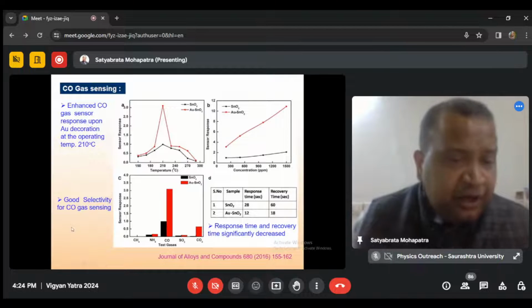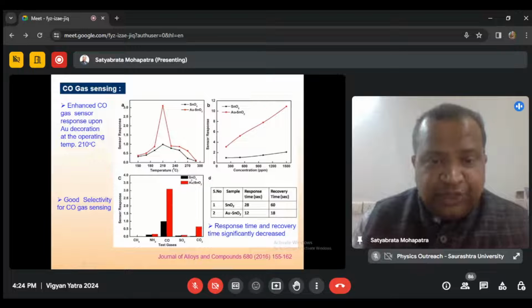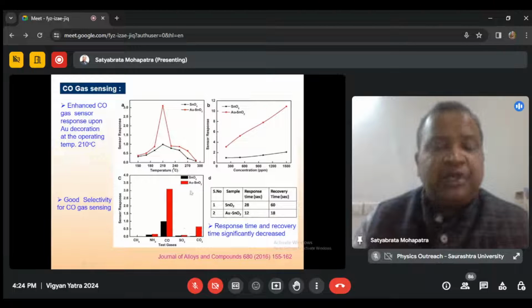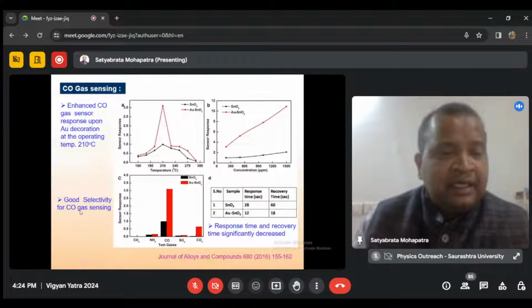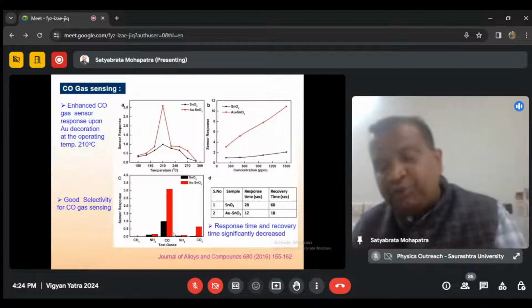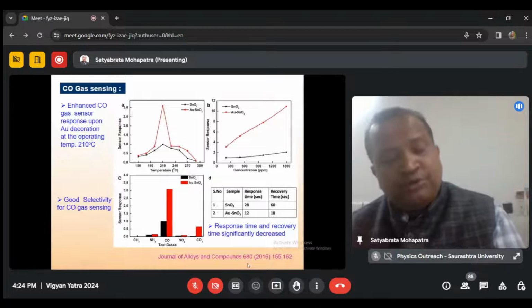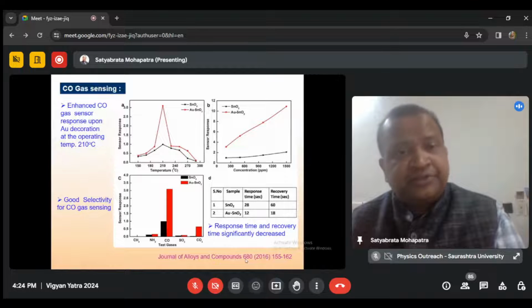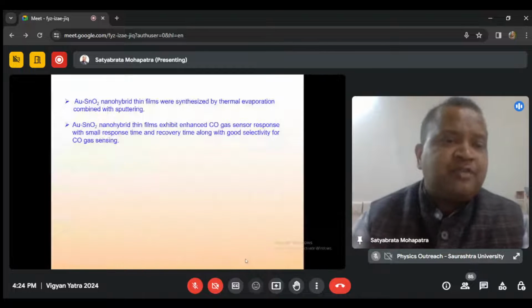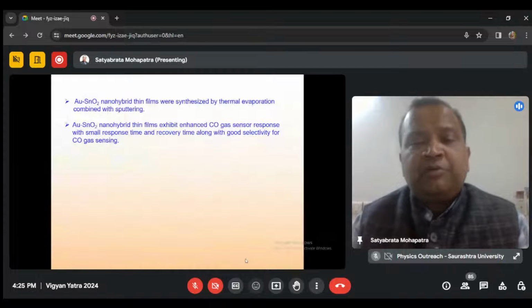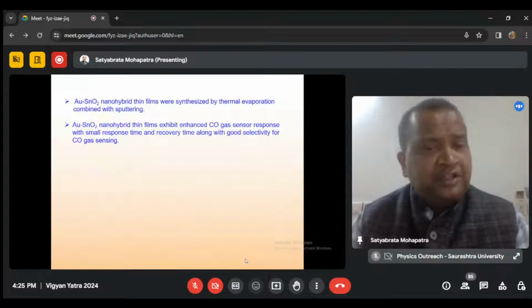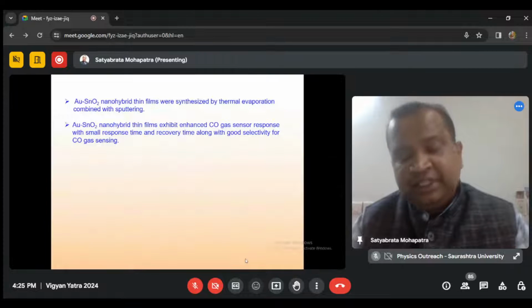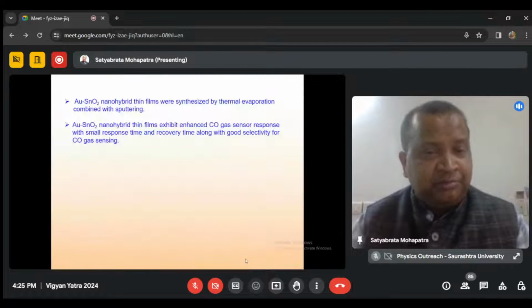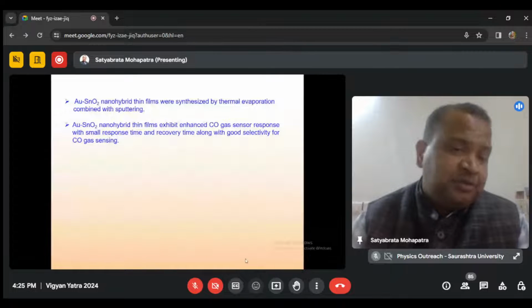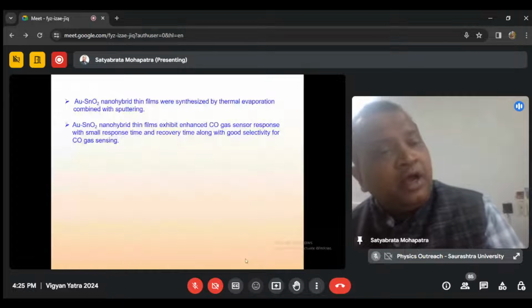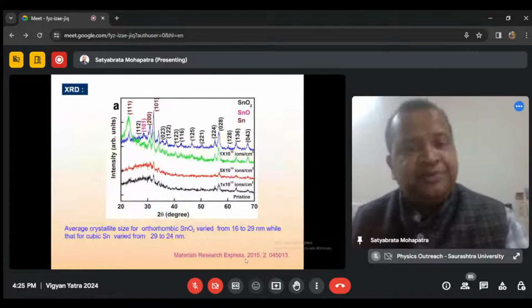Now, the next thing is to check whether they are selective. You can see clearly that as compared to tin oxide, the gold tin oxide plasmonic nanohybrid film shows excellent selectivity for carbon monoxide. This work was published in the Journal of Alloys and Compounds in 2016, and this is from Neha's thesis. So we have prepared these plasmonic hybrids, and they show enhanced carbon monoxide gas sensor response with a small response time, recovery time, and very good selectivity, which makes them a very promising material which can be grown even on a larger area, and hence one can directly go for it.